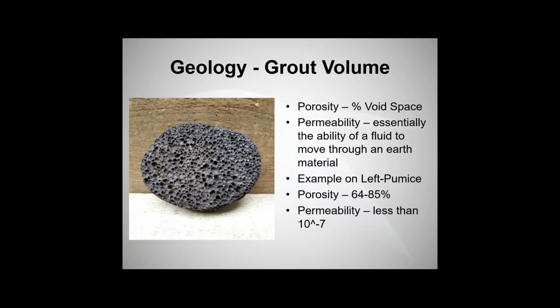To demonstrate why it may not be right all the time, this rock shown here on the left is pumice. All of these little black spots indicate air bubbles in this pumice. So that's void space that's in this material, and this void space is really not connected. Even though this is rock and it's easier to see here, that premise can also work in soils. So that presents a problem if you're looking at porosity, which again is percent void space.